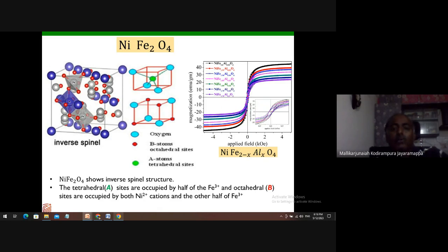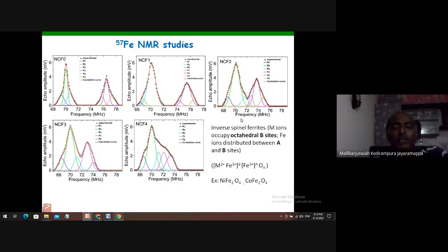For that kind of system, I need to rely on internal field NMR. What internal field NMR tells us is, whenever I record 57Fe NMR and vary the operating frequency of my spectrometer, I get a signal. At 68 megahertz it doesn't show anything. After that, if I keep increasing, it goes through a maximum value and again comes back, and at the higher end again it goes up and comes back. These two peaks: the low frequency peak corresponds to B sites, and the high frequency peak corresponds to the A site. I can distinguish where exactly my iron is going and sitting.